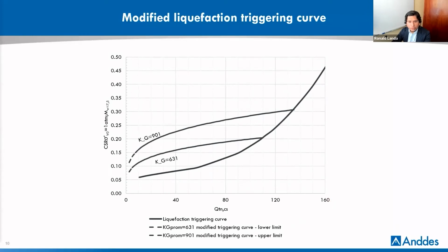As reported in the Kg figures, where Kg ranged from 631 to 901, we redefined the relationship of the CRR as a function of the threshold cyclic shear strain and the Kg, of course, as provided in the preceding equations. So the liquefaction triggering curve can now be modified as depicted in these dashed lines, until reaching the standard liquefaction triggering curve.